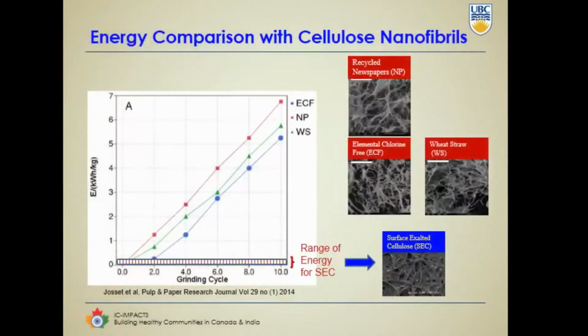Now, there is a great deal of work going on in nanocellulose. Of course, there are nanocellulose, nanofibrils, and nanocrystals, which are being utilized. So these are some of the nanomaterials that we are using. These are very highly fibrillated. And if you look at the energy absorption in this nanofibrillation, you will notice that it takes up to 5,000 kilowatt hour per ton for producing these nanofibrils and nanocrystals.